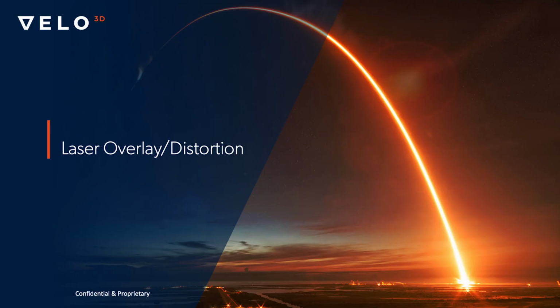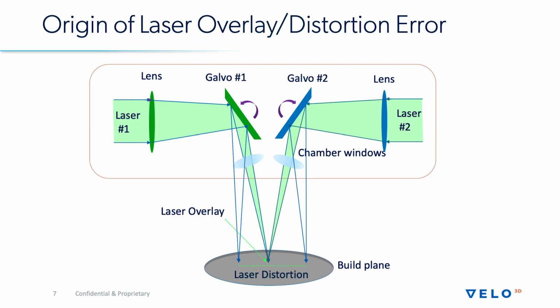The second thing I want to talk about is laser overlay and distortion. This is a schematic of a multi-laser system. And this schematic would be pretty general for any multi-laser laser powder bed system, but this one specifically is for the Velo 2-laser Sapphire system with two 1 kilowatt lasers. So in this case, you've got two different lasers up in the optics box that are both impinging upon their respective galvos, and they're being directed onto the build plane. The idea is that if both lasers are told to fire at the exact same spot on the build plate, the laser beams actually end up at the same spot of the build plane.